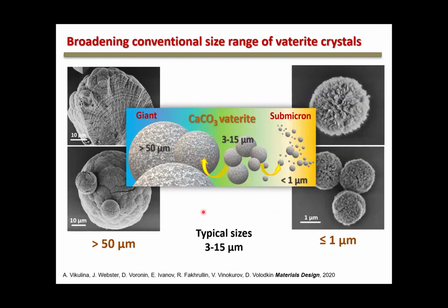Right now, typically the size of calcium carbonate particles that you can easily prepare in the lab is some microns, up to, let's say, 3 to 15 microns. This is the conventional size range. But now we published rather recently a paper on how one can prepare such particles in the lab in a simple procedure without any additives at all, making particles either huge, really giant, so you can see a single particle by your eyes actually, or very small, in the sub-micrometer range. So basically they're already nanoparticles.